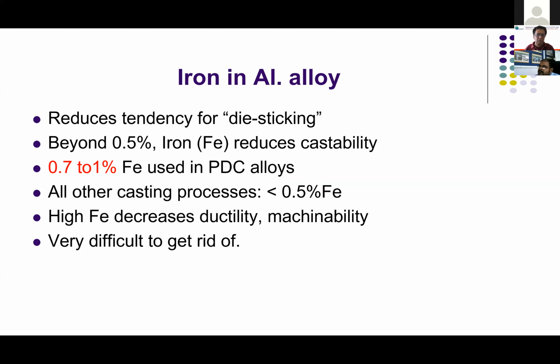Now, even if you go to the smelter where the pure aluminum is produced, the major impurity is iron. Aluminum has got a high affinity for iron, right? Beyond 0.5% iron reduces the castability. So we normally recommend iron below 0.4. For low pressure and gravity, ensure that iron is below 0.4.